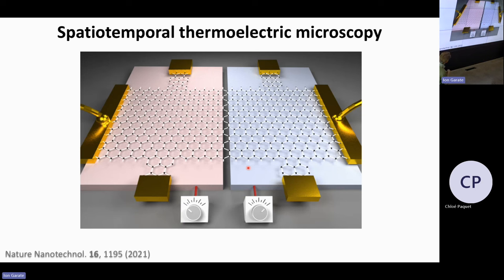So we have a sample that is also a Hall bar, so we can do electrical measurements and get mobilities. Again, we can change the potential, change the Fermi energy, get a PN junction, and get a photovoltage, which is in the end what we're going to be measuring. So in this case, again, it's an optoelectronic measurement. We shine light, but we probe currents or voltages.